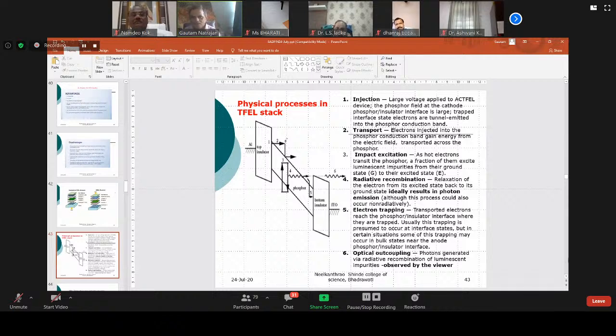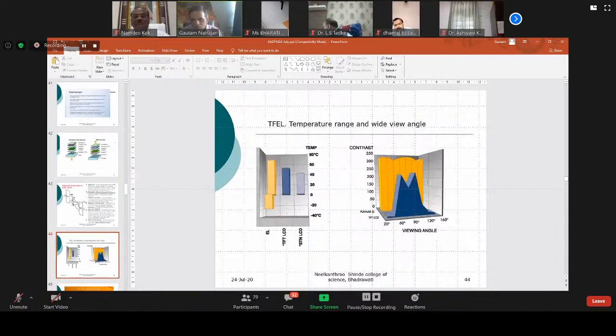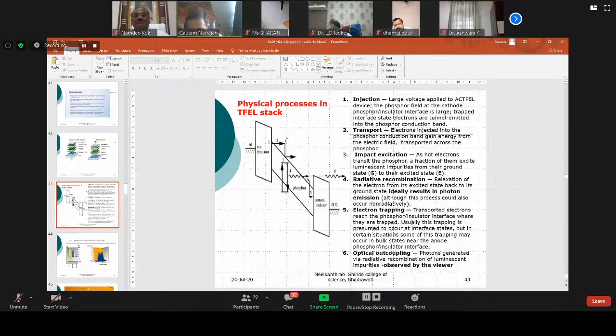The process in AC electroluminescence: injection, large voltage applied, and the field at the cathode-phosphor interface is very large. Trapped interface state electrons are tunnel emitted into the phosphor, which means the insulator is protecting the phosphor. The electron is injected into the phosphor conduction band. If it goes to the conduction band, it gains energy from the electric field and moves at high velocity. Then it hits the luminescent ion, like copper or manganese, the dopant ion, and it emits light. The radiative recombination leads to light. Then some electrons can remain at interface states. Then optical outcoupling: whatever light is emitted has to be coupled out.